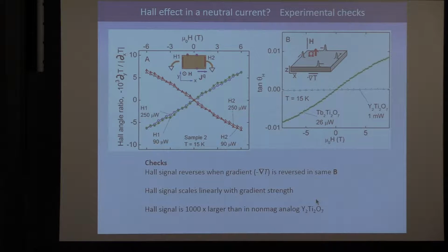So here are the initial experimental checks. Max, the student doing this, Hirschberger, Max saw a very large thermal Hall effect. And this is always nervous, right? Because you're looking for it and you find a big signal. So you want to make sure that it's real, that you're not making a fool of yourself when you publish it. So one of the tests is to reverse the heat current.